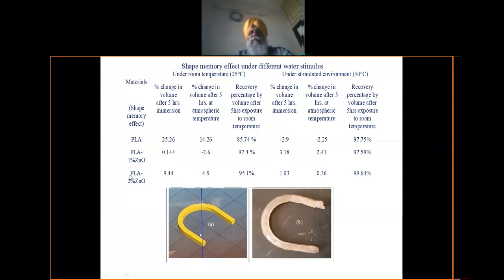So what we observed is that for 1% ZnO at 25 degrees Celsius temperature, it was able to regain its shape in the form of volumetric contraction or expansion up to 97.4%. Whereas once this material was observed at 40 degrees Celsius, the recovery rate was higher. This gives us input that this material is going to have two types of stimulus. One stimulus is the temperature and the second stimulus is the moisture, right? So what we call a hydrothermal effect. So for this particular composition that we were talking about, in place of one stimulus, there were two stimuli: one is the temperature and another is the moisture.